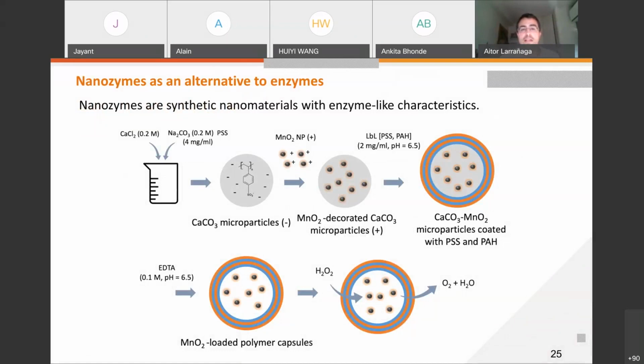So to incorporate these manganese dioxide nanoparticles in our sacrificial template, we slightly changed the fabrication process of the sacrificial template. Here again, we use the precipitation method by simply mixing calcium chloride and sodium carbonate aqueous solutions. But in this case, we incorporated a little bit of polystyrene sulfonate in this precipitation process. So the resulting calcium carbonate microparticles had a strong negative charge. This strong negative charge was very important for the subsequent incorporation of the positively charged manganese dioxide nanoparticles, which were finally incorporated in our core by electrostatic interactions.